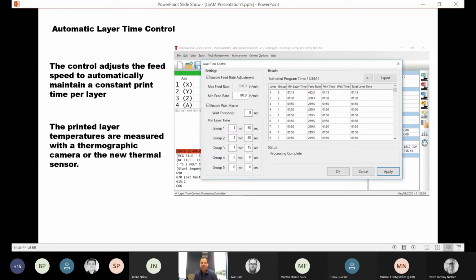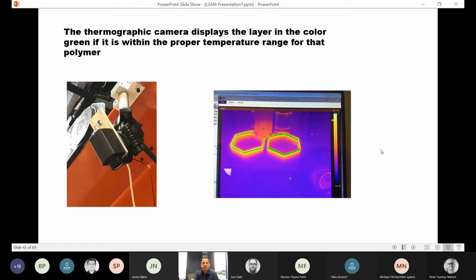Automatic layer time control. This controls the feed speed to automatically maintain a constant print time per layer. The printed layer temperatures are measured with a thermographic camera or the new thermal sensor, which we just introduced a few weeks back. The thermographic camera displays the layers in the color green if it is within the proper temperature range for that specific polymer that's being printed.